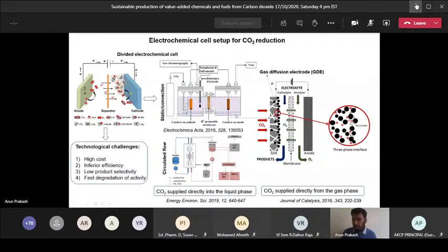When you increase the concentration, the Faraday efficiency actually drops. So it is preferred to use 1 or 2 molar electrolyte, which is enough for the CO2 reduction, not more than that. The concentration of the electrolytes should not exceed 1 or 2 molar. And here you can see the pressure scale. With an increase in the pressure, the Faraday efficiency also increases. But whenever you are dealing with pressure, you should be very careful.